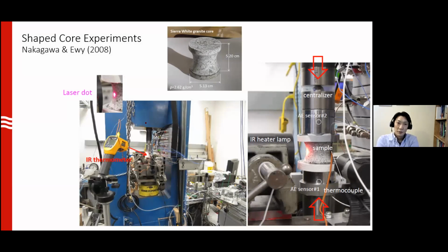In this experiment they use a rock sample that has a particular geometry with a narrowed center section. I'm sure this is similar to the dog bone shaped experiments that you have also been doing in the past. But the reason they do this experiment here is not to create tension, but to intentionally create a stress concentration in the middle that is similar to the curvature of the borehole. By loading axially, they can cause a simulated hoop stress at the side of the rock.